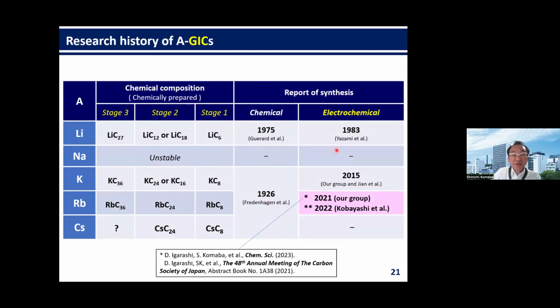In the case of electrochemistry, of course, lithium was already reported more than 40 years ago. In the case of sodium, it is very unfortunate that sodium cannot intercalate into graphite. But potassium, rubidium, and cesium can intercalate, not only by chemical but also by electrochemical reaction. This means that the larger size of potassium is not the reason for no intercalation of sodium, because the larger potassium, rubidium, and cesium can intercalate into graphite with very high reversibility.